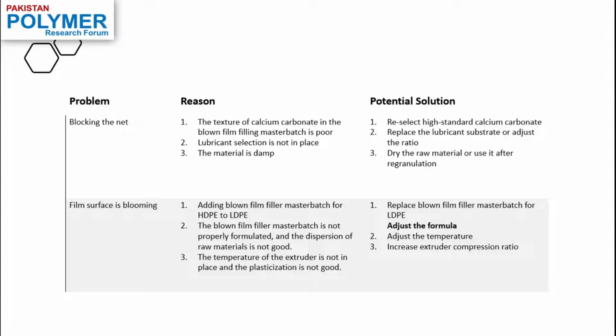Well, you can see that the calcium carbonate is actually available in so many forms and so many types, and it's really important to choose the right type of calcium carbonate, the right texture, the right color, the right purity, and the right particle size to cope with all these problems. And secondly, you have to either replace the type of the lubricant you're using, or adjust the ratio or the amount of the lubricant you're using. And generally, we use oils and waxes as the lubricants in making the master batches. It's really important to adjust the ratios in the overall formulation and to select the right type of lubricant.